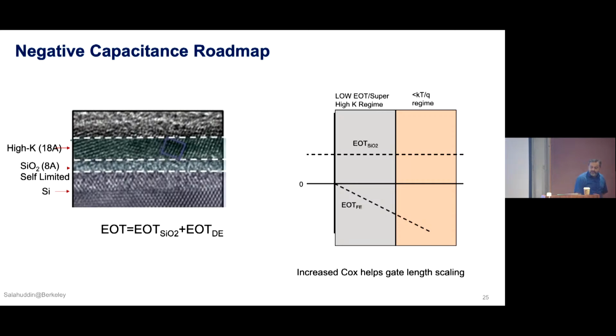Okay, so where are we going with this? What is the roadmap here? Right now I showed you a result with 6.5 angstrom EOT. Now in the group, we can go down to around 4.5 angstrom EOT. So over the years, we are slowly coming down, and we will continue to go down. That's the roadmap. And at some point, we even want to go below 0. In other words, we will have this layer contribute more than -8 angstrom to the entire stack, so that silicon can directly see the negative EOT effect. That's where we are going.